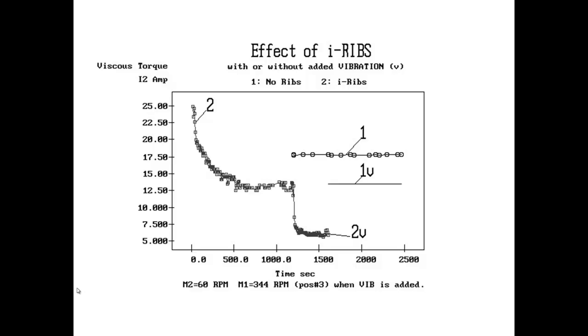That's 1V. Now if I put ribs on both surfaces, the facing surfaces of the barrel and the rotor, I see that with just pure rotation, this is curve number 2, I obtain in steady state a value which is equal to 1V, as if the vibration was created from within. And that's what I said. I said that the set of intelligent ribs created vibration from within, without the requirement of using an external motor, and this is proved here.